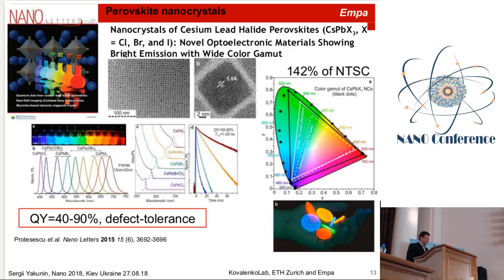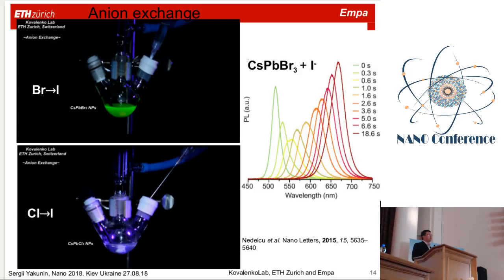And then, in order to highlight the interest in this paper, a couple of years after publishing, it now has around 1,200 citations. And another very cool feature of this material is that after cooking, you can still modify optoelectronic properties. So actually, it has the ability for anion exchange. So this halide composition you can change after the synthesis.